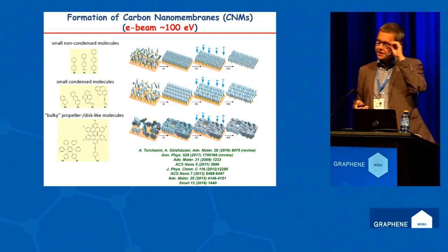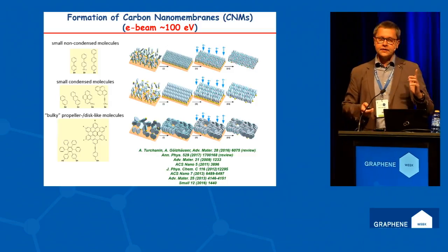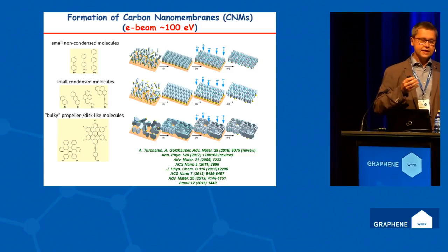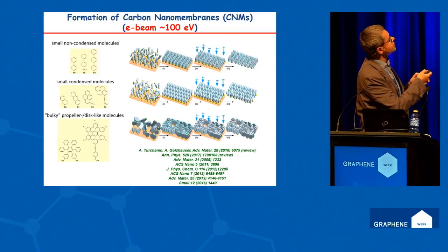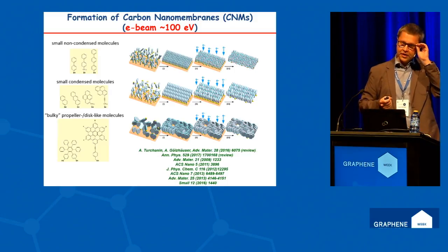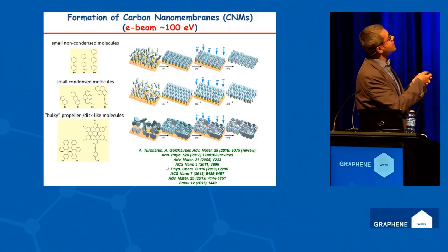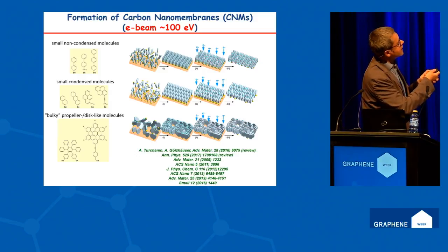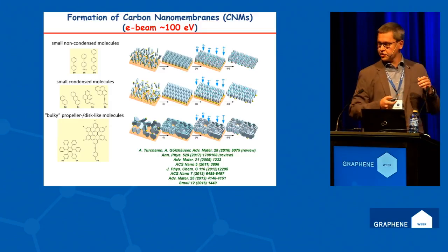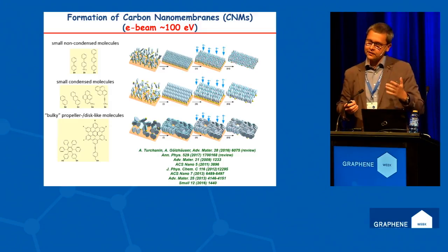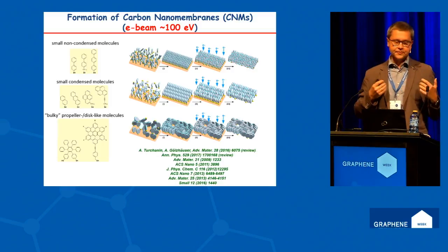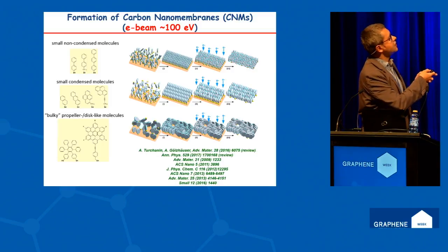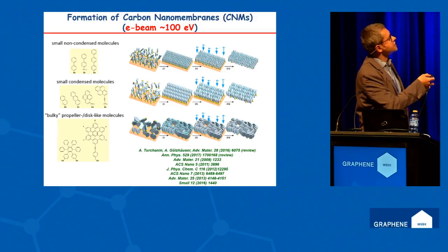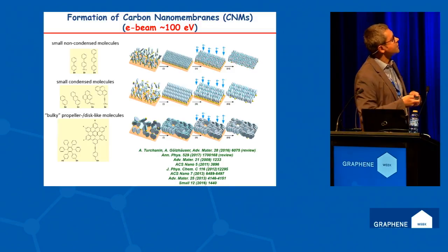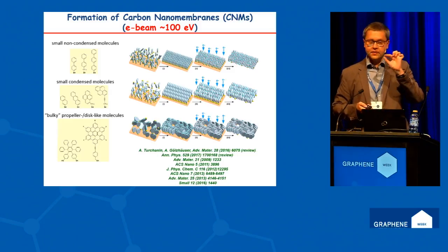Low-energy electrons, this is another example where we have been working for quite some time. This is the conversion of organic aromatic self-assembled monolayers, using template-induced synthesis, into a material we named carbon nanomembranes, which are basically molecular nanosheets. By making a self-assembled monolayer on such a surface, you can again, by irradiating the structures with an electron beam, cause the cleavage of carbon-hydrogen bonds and fusing of these molecules with each other, and synthesis of such carbon nanomembranes with only one molecule thickness.